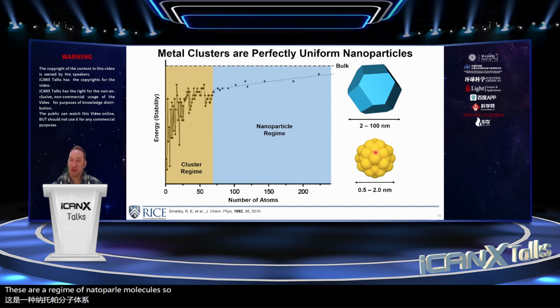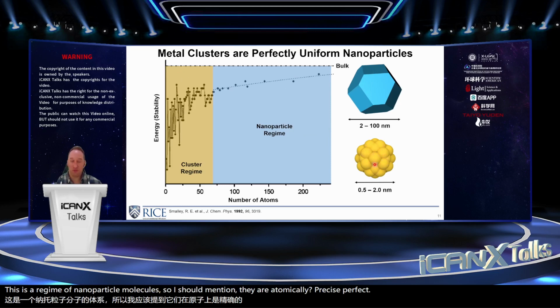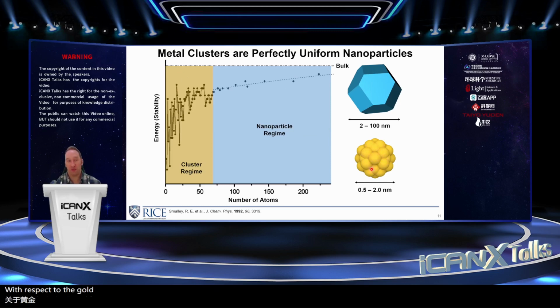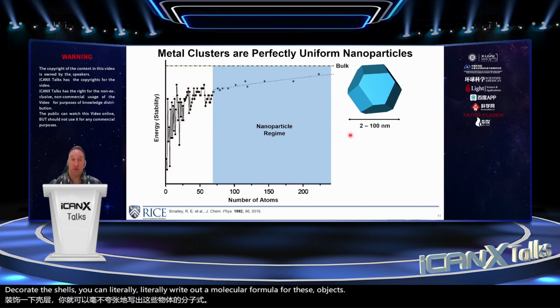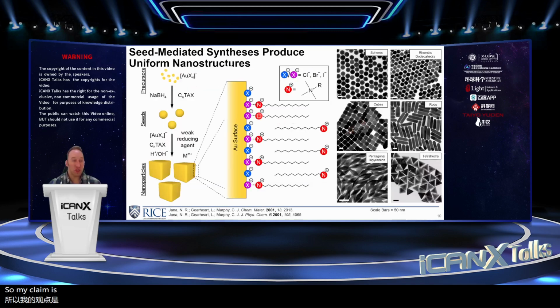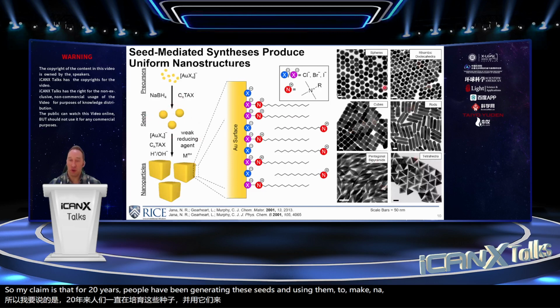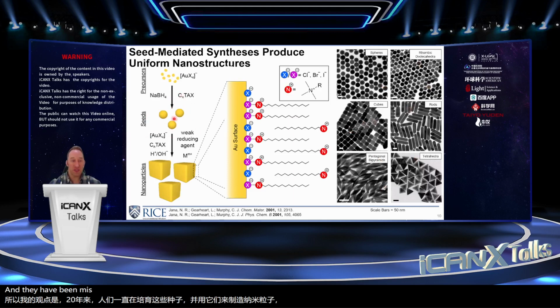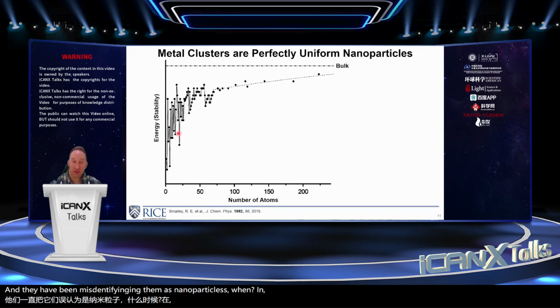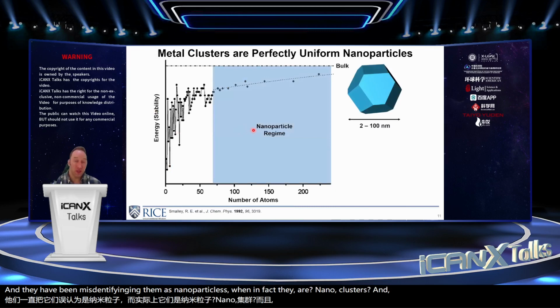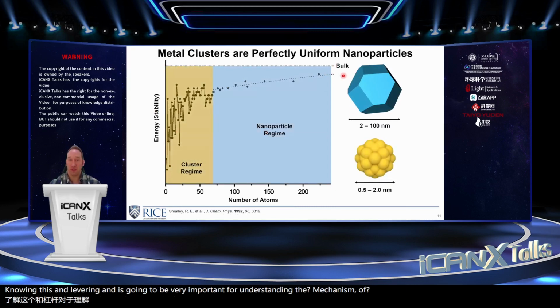So I should mention they are atomically precise, perfect, with respect to the gold atoms, the atoms in the core, and also with respect to the ligands that decorate the shell. So you can literally write out a molecular formula for these objects. So my claim is that for 20 years, people have been generating these seeds and using them to make nanoparticles, and they have been misidentifying them as nanoparticles when in fact they are nanoclusters. And obviously, knowing this and leveraging it is going to be very important for understanding the mechanism of these reactions.